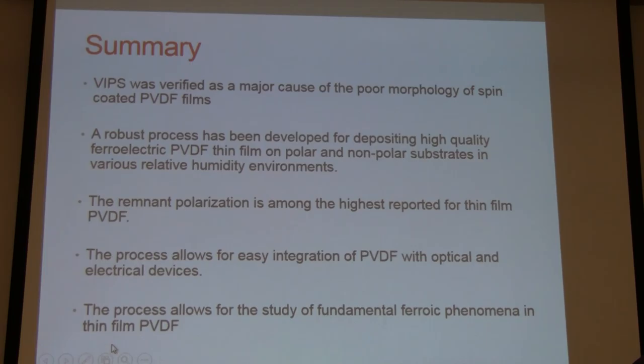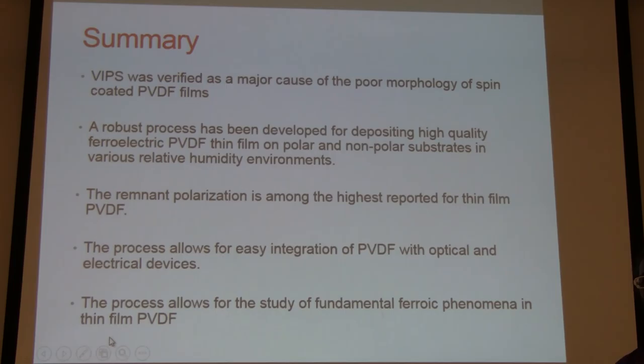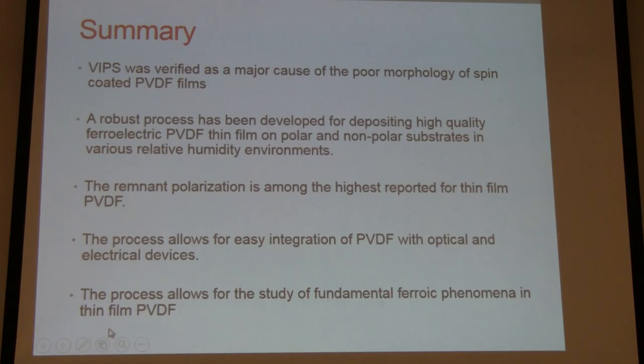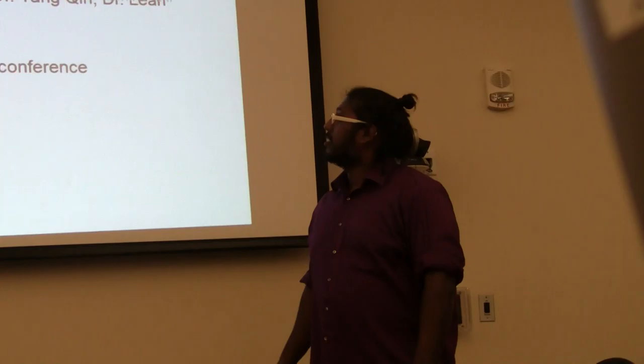So in summary, we verified that vapor induced phase separation was the cause of the poor morphology of the films. And then we developed a robust process to be able to put these films on polar and non-polar substrates, aluminum oxide versus gold. And then, we saw from those hysteresis loops, those hysteresis loops are one of the best ever reported for this film. And that this process allows for the integration and study of the fundamental physics of ferroelectrics.